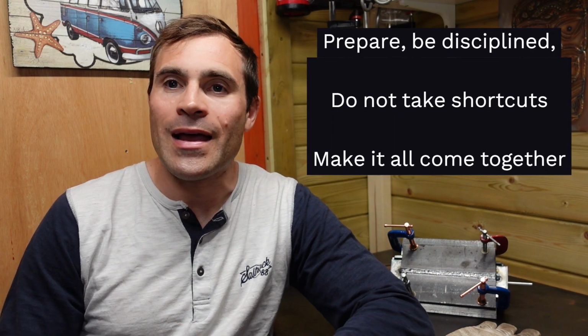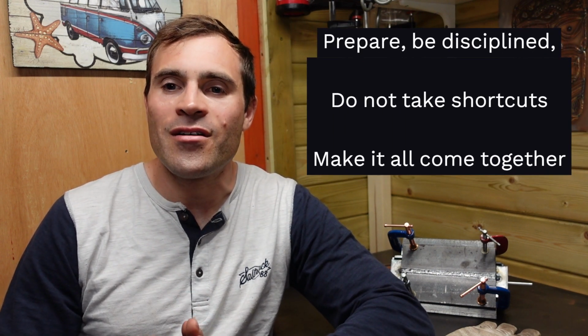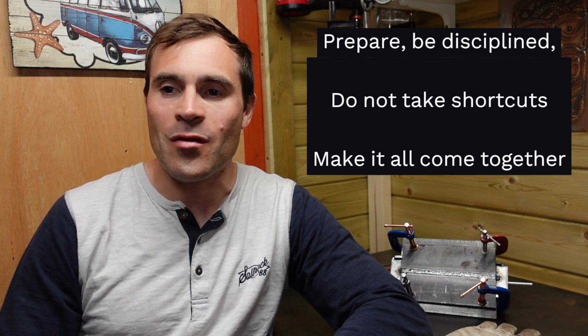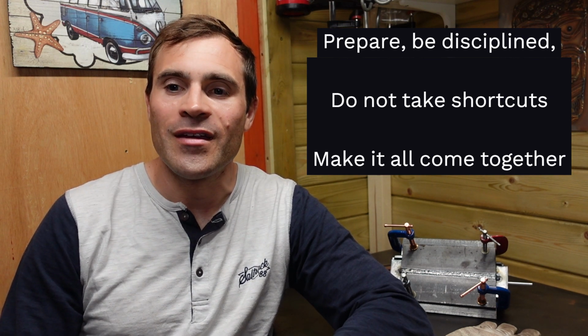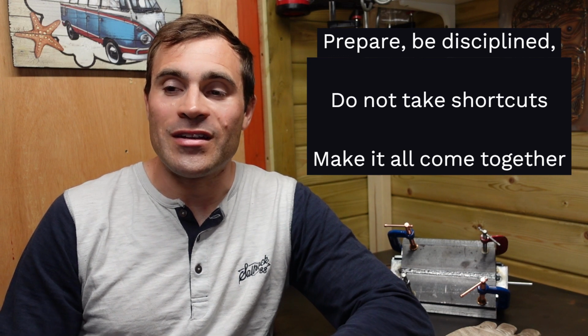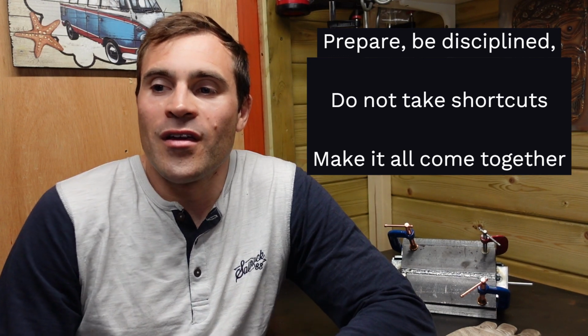Whilst that's cooling down, let's have a quick recap on what we've covered. So if you weld to pass X-ray, first and foremost, your preparation has got to be absolutely perfect. That's your bevel, your root edge, your root gap, the TIG wire you use, the purge, how the plates are actually set up in a way where they're not stepped or they don't move, and everything throughout the weld itself. Making sure it all runs smooth, the correct TIG wire, the correct techniques, taking your time, don't rush it, and if something's not right, stop what you were doing, make it right, and then carry on.